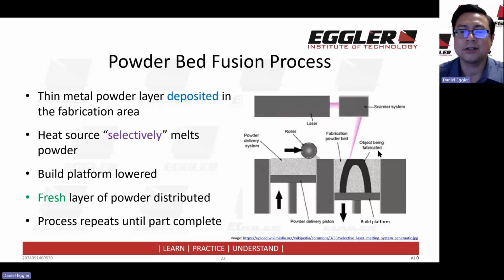There are some limitations and issues with powder bed fusion, particularly if you think about residual heat in the near vicinity of the melt pool. We often have formation of a skin. This is where partially melted powder adheres to the main part. And there are some other issues as well. I won't get into them here, but it's important to note that the key challenge with powder bed fusion is the repeatability of the process, in particular with powder management. So there needs to be a very effective strategy in terms of managing the powder, because as you are heating and reheating and cooling the surrounding powder, over time this can change the powder properties, and this can obviously then affect the build. So powder management is a very key issue when it comes to powder bed fusion.